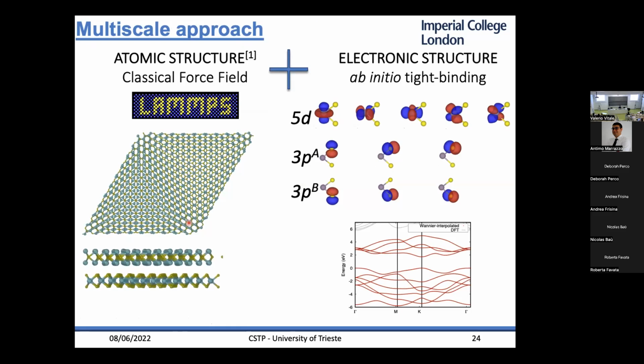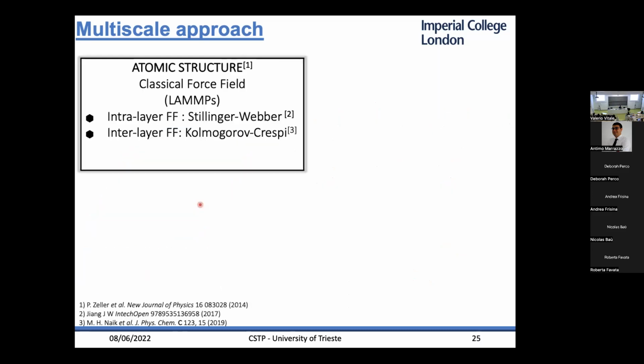So we use this classical force field to generate the atomic structures, which have been parameterized on density functional theory. And we use this ab initio tight binding, which I will explain, that basically uses Wannier functions on the unit cell to generate the band structure of these systems at the Moiré scale. And these have also been parameterized on the DFT calculations. So basically, the bottom line is we use DFT to parameterize these systems in the unit cell, which only contains 3 or 2 or 6 atoms, depending on the system. And then we use this parameterization on the unit cell to compute the structure and the electronic structure at the Moiré scale.